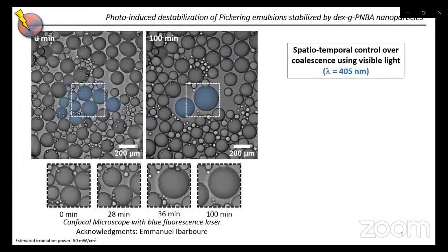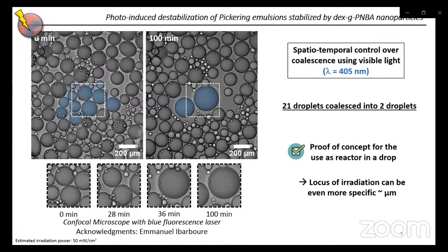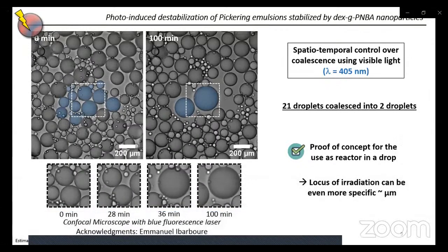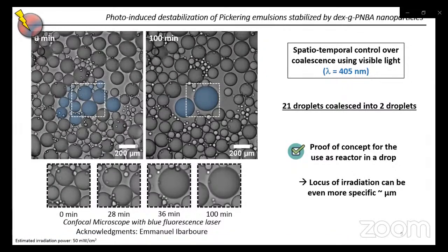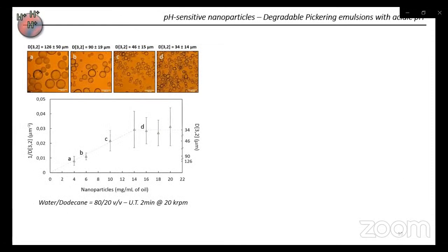We also performed quite the same experiment, but this time with visible light, which is quite an improvement because nitrobenzyl groups are only sensitive to UV. And thanks to these confocal microscope experiments, we were able to localize the irradiation in a specific area, and 21 droplets, which are colored in blue here, coalesced into 2 droplets in 100 minutes. So this is quite a good proof of concept that we can use our system as a reactor in a drop process. And specifically, the locus of irradiation can be even more specific, as we can maybe go down to micrometers.